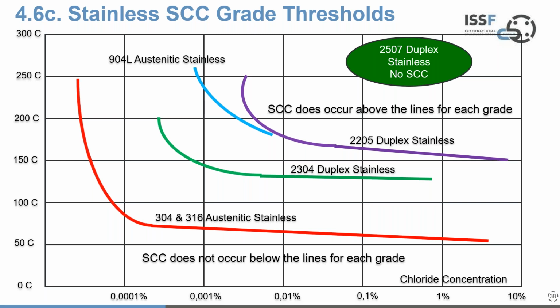But there's also things like the super austenitic stainless steels. So 904L super austenitic can tolerate a reasonable amount of chloride concentration and quite high temperatures. And when you move to the real super duplex grades, the 2507, this is really not susceptible to stress corrosion cracking within the sort of boundaries of this diagram. So this is really an indication that you have to think about the environment and the temperature to choose the right stainless to avoid this phenomenon.